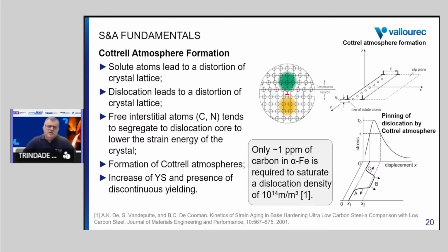And this is what comes to the important phenomenon, which is the Cottrell atmosphere formation. We know that the free interstitial atoms like carbon and nitrogen tend to diffuse to regions where you have dislocations, trying to lower the strain energy of the system. Those elements will diffuse towards the dislocation core and saturate it. For example, we just need 1 ppm of carbon to saturate a dislocation density of this level. So we need a small amount of element to form the Cottrell atmosphere.